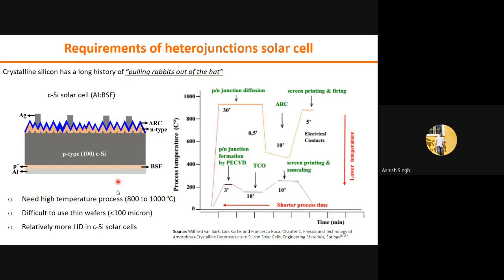The major disadvantage in this technology is that it requires a high temperature process, with temperature between 800 to 1000 degrees Celsius. Junction formation happens in the range of 900 degrees Celsius. That is very high temperature for industry. Due to this high temperature process, the thermal budget goes up, and they cannot reduce the price of the solar cell. Also, the process time is very high, so the production rate will be slow compared to other solar cell technologies.